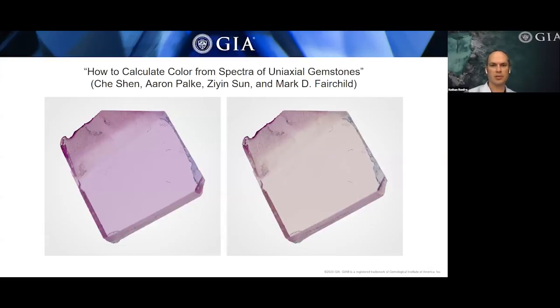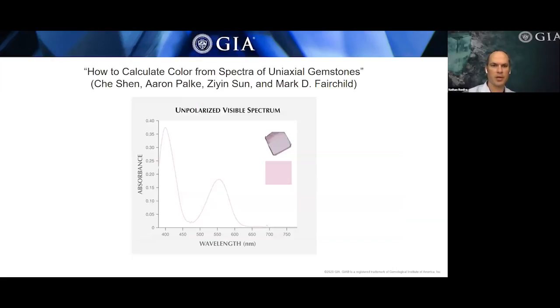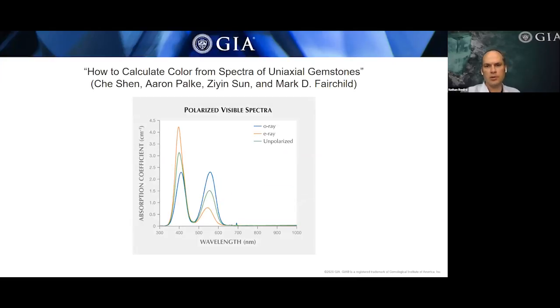Here's one of the main samples that they used, which was a corundum wafer. So it's carefully oriented so that you can collect unmixed, polarized, ordinary and extraordinary ray spectra. So ordinary rays on the left and extraordinary ray colors on the right. And when you combine those 2 spectra, you get an unpolarized spectra. So to deconstruct the spectra, you have to measure the polarized spectra, and then using transmittance, you can add those two components together to produce the unpolarized spectra. So here's the figure that shows the unpolarized spectra and the component parts, the O ray and the E ray, and the green trace represents when those two components are added together, you have the unpolarized version, and that unpolarized spectra is representative of what your eye would see in a face-up stone, which is the mixture of the E and the O ray.